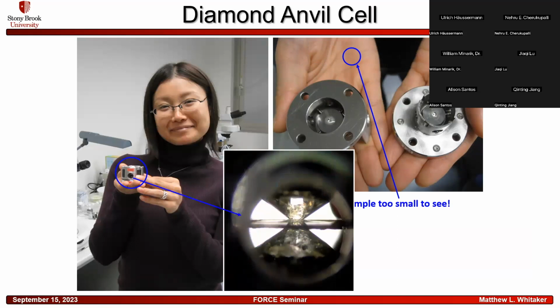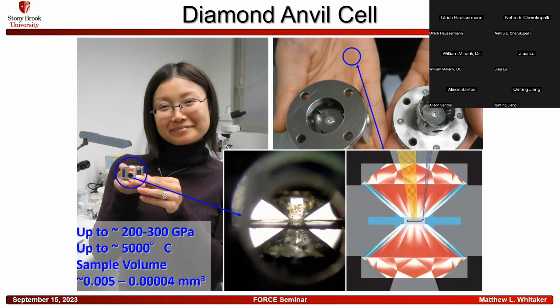The diamonds come together and compress around a gasket which contains the sample material that you're interested in, and you can squeeze those together and reach much higher pressures because, again, pressure is force divided by area, and in this case the area is very small, so it requires relatively little force to be able to produce high pressures. And this regularly can go up to 200 to 300 GPa and 5,000 degrees Celsius with laser heating. But again, the sample volume is very small.